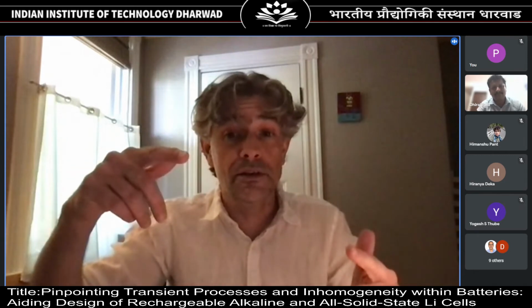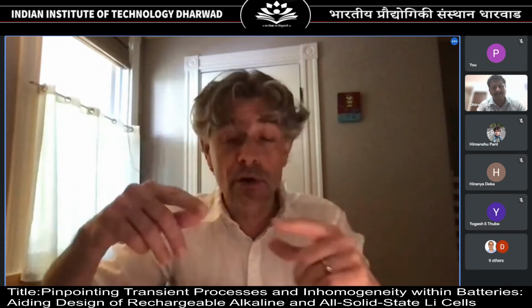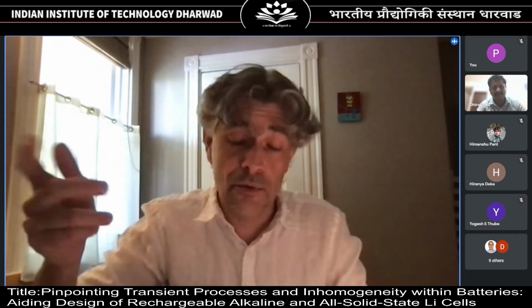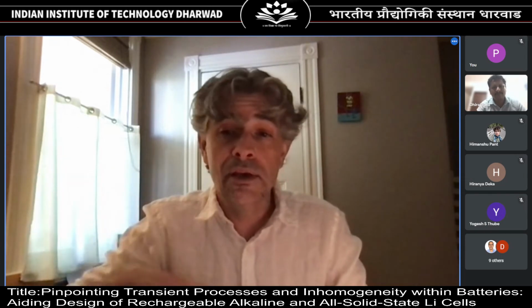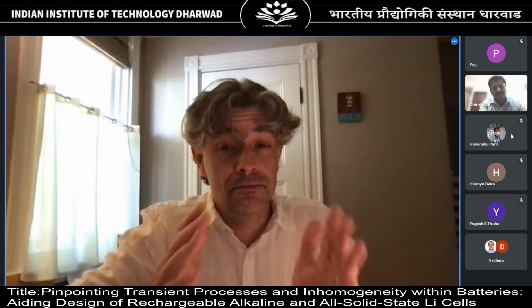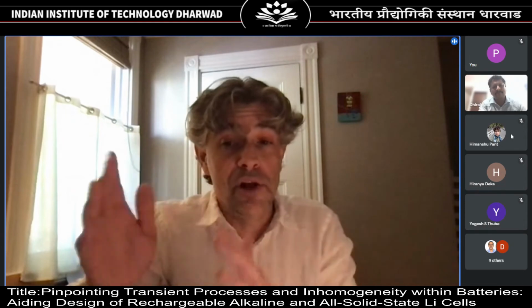It's a nonlinear equation. But also, it had two terms. So the reaction can run to the left or run to the right, usually. It can go forward or backward in an electrochemical system. And if you use a Tafel expression, that's just one part of the exponential. And Butler-Volmer is both terms of the exponential.